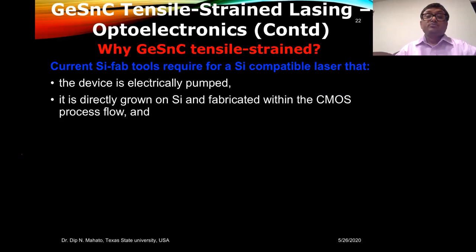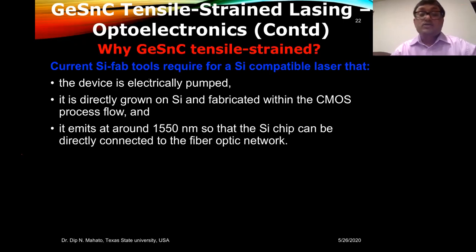And also it has to be fabricated on silicon within the CMOS process flow, complementary metal oxide semiconductor process flow, the process flow that I talked about briefly. And then it has to emit around 1550 nanometer, so you can use the chip and connect to the fiber optic network for their use in the sensors. Okay, so those are the requirements.